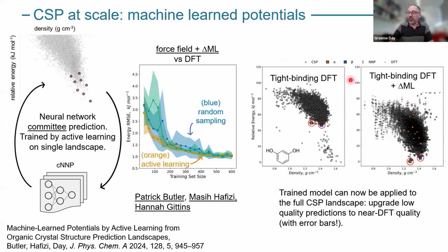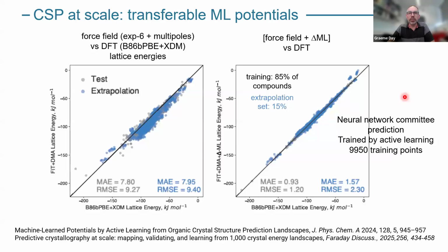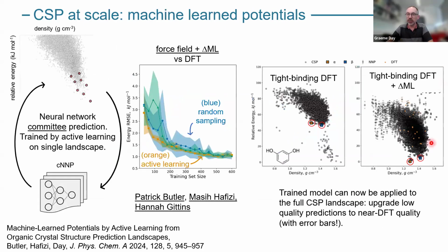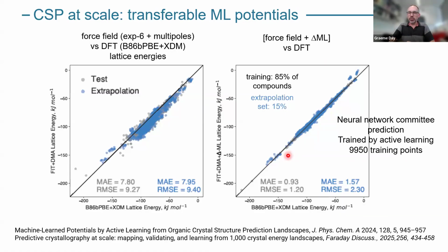And the nice thing about that is you can do predictions quite quick with cheap methods, and applying this correction can also be done quite quickly. Now we're doing that based on a database of 1,000 molecules. So this work here was trying to correct a single landscape. Okay, so it was a model which only knew about this molecule, resorcinol. What we're interested in now is trying to make a general prediction. So we can always use this force field and we can always correct it to something which approaches DFT energies.